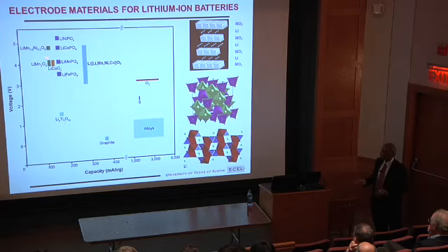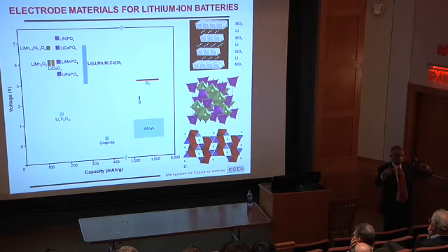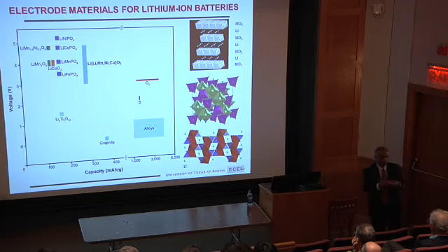But that has a very basic chemistry problem. Mn3+, in the presence of a very trace amount of acid, two Mn3+ will come close to each other. One will become Mn2+, one will become Mn4+. Mn2+ is soluble, Mn4+ is stable in acid. So that's called disproportionation, and that is what is killing this material. So that's why it was not used for so long.